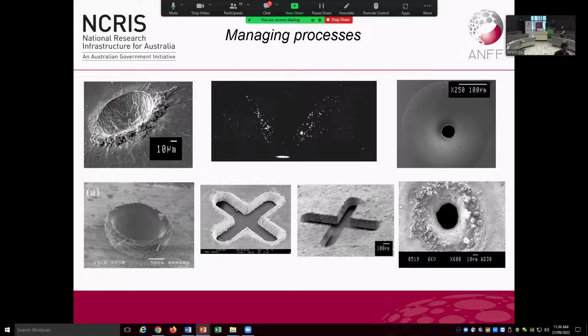These are some examples of some pretty suboptimal machining. The picture that I have in the middle is a silhouette of the phase explosion I spoke about before. This is in copper, and we've just got a whole ejected mass of molten particles, which will hang around on the surface and be quite problematic. You also see that if we're machining in these regimes, we're generating quite a nasty edge burr on some of our features, and we don't want to be leaving edge burrs like this around, okay?